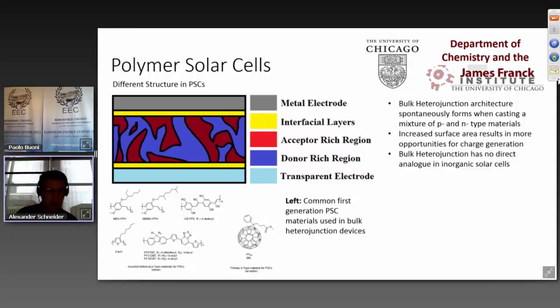All right, and now below the cartoon you can see several examples of different P-type donor materials that were common about 10 years ago, and these were a number of materials with lots of different band gaps and lots of different solubilities in organic solvents. So they had very different properties, but similar efficiencies. So it's quite impressive, actually, that all these wide variety of different architectures are able to spontaneously aggregate into these structures, and no matter what different material we start with, we end up getting this bulk heterojunction structure, which forms a solar cell and can absorb light and generate electricity.